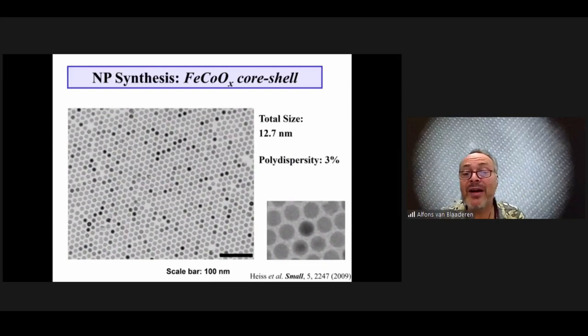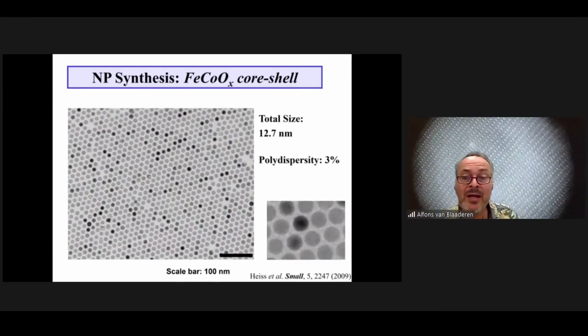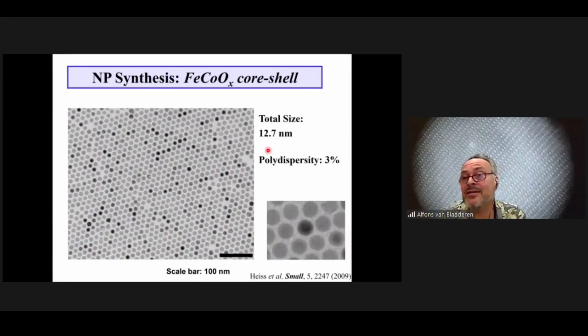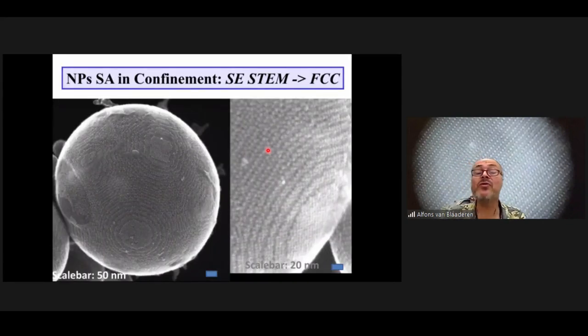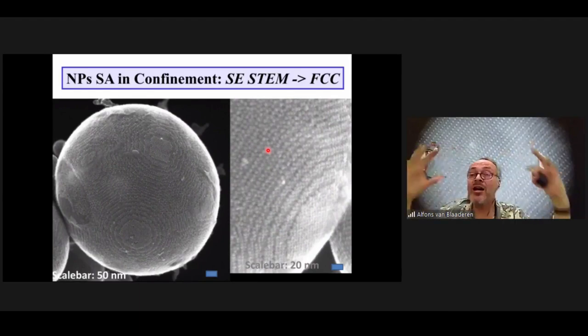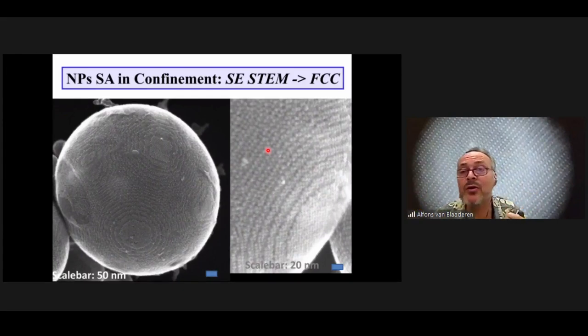So what we found already 5 years ago, and that's why I go very quickly about it. We did this with iron oxide nanoparticles, which can be made very monodisperse. The polydispersity in size can be as small as a few percent. They have a single crystalline property inside the particles, which is important for some applications. What we found is that for very large superparticles, we found what we expected. If you dry them slowly enough, you get face-centered cubic crystals, which some of you might even be able to recognize from this ABC stacking. These are beautiful, single crystalline, very large supraparticles.